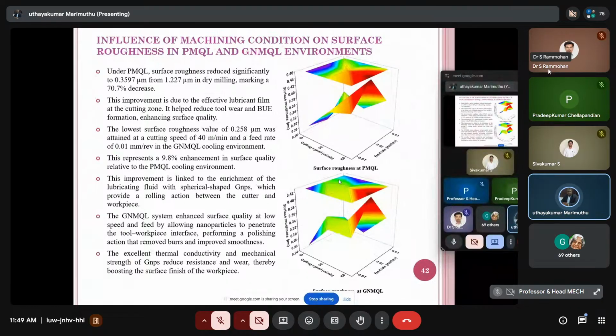This improvement is due to an effective lubricant film in the cutting zone. It helped to reduce the tool wear and built-up edge formation, enhancing the surface quality. The lowest surface roughness value of 0.258 micron was attained at a cutting speed of 40 meters per minute and feed rate 0.01, right? This represents a 9.8% enhancement in surface quality relative to PMQL.